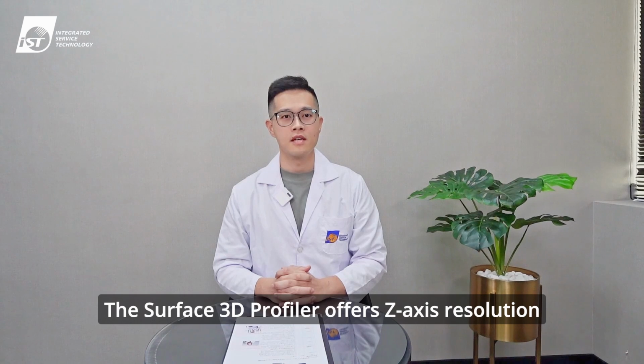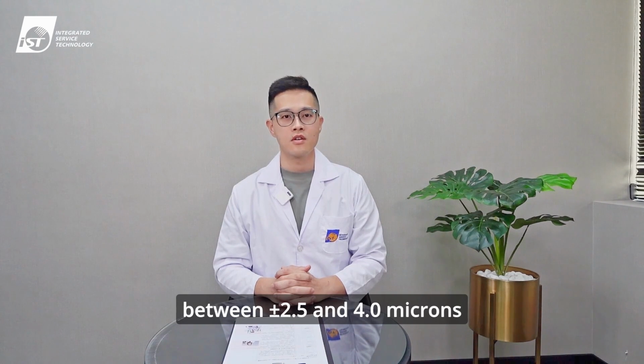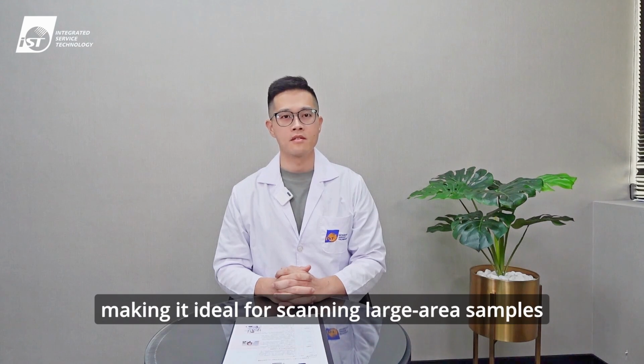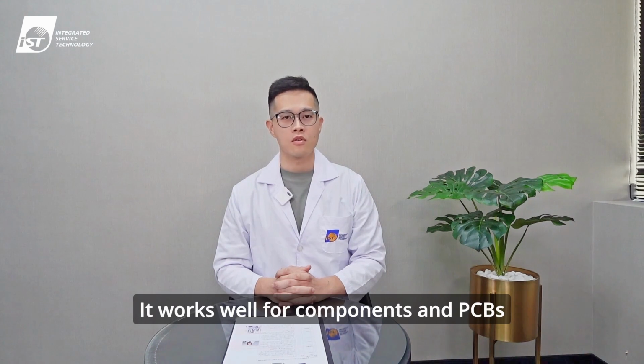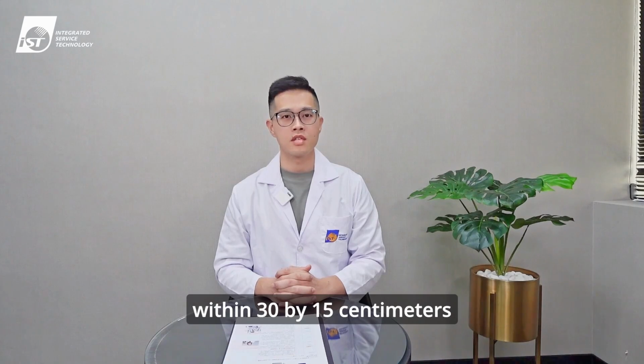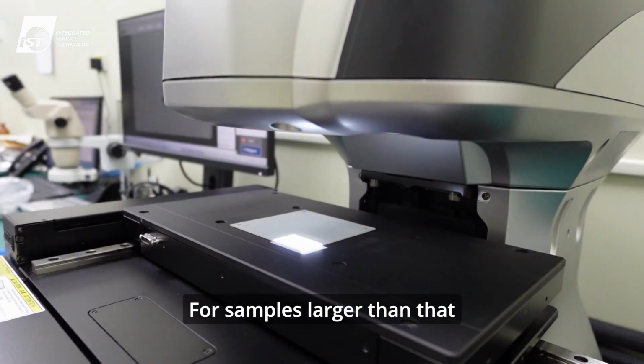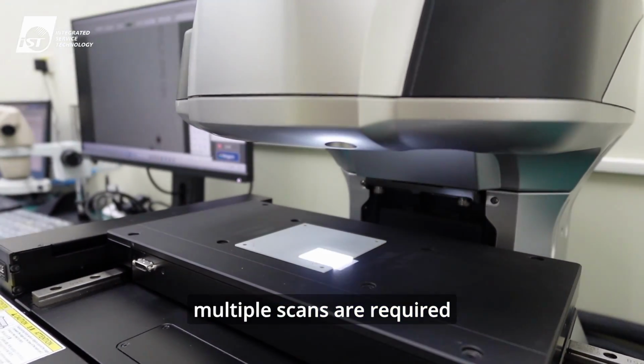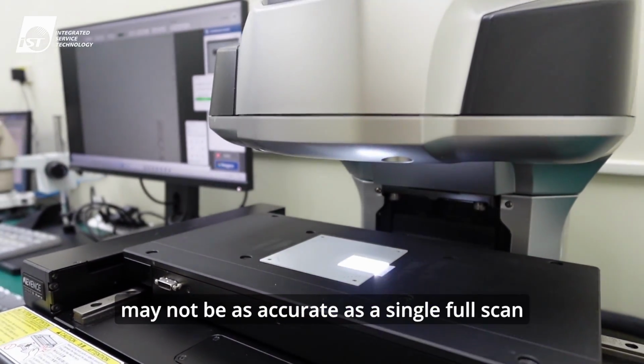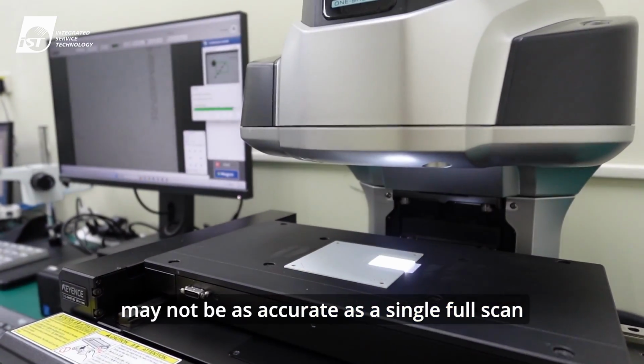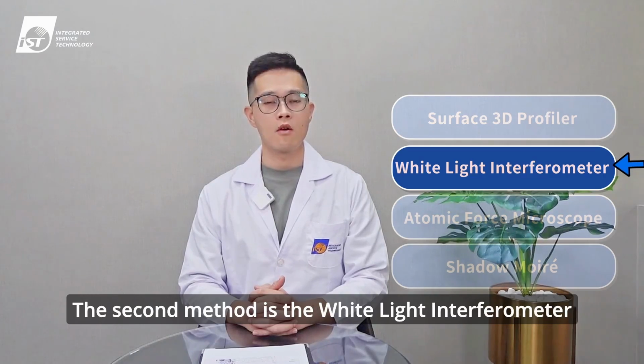The Surface 3D Profiler offers Z-axis resolution between plus or minus 2.5 and 4.0 microns, making it ideal for scanning large area samples. It works well for components and PCBs within 30 by 15 centimeters. For samples larger than that, multiple scans are required and the stitch results may not be as accurate as a single full scan.